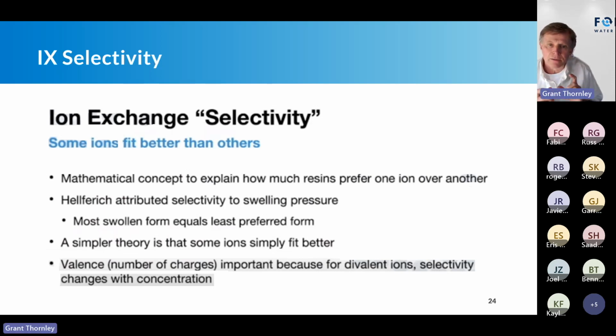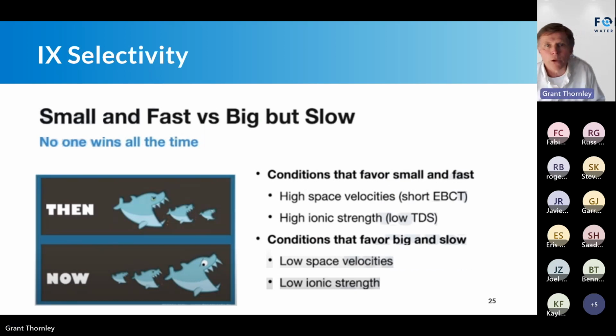And selectivity, another for polishing. For trace, an important concept to remember is selectivity changes with concentration or TDS of the solution. So TDS, particularly in trace polishing, can have a significant effect on the efficiency of the ion exchange. So a quick way of taking a look at selectivity is, I borrow this from the internet.